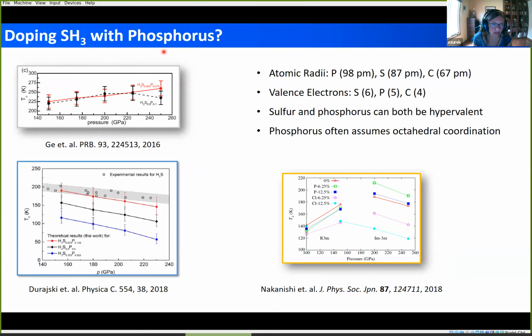So we also took a look at what would happen if you doped SH3 with phosphorus. We note that what is different between carbon, sulfur, and phosphorus is that the phosphorus radius is much more similar to sulfur than the carbon radius.